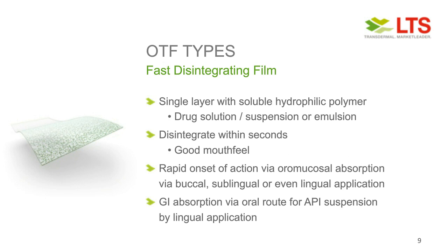The fast disintegrating films can achieve a rapid onset of action, mainly via the oral mucosal absorption of the drug. This can be achieved while the film is applied buccally, sublingually, or even by just a lingual application. It really depends on the permeability of the drug. But with the fast disintegrating film, we can also achieve just another oral application, basically, with the absorption through the GI tract, when the API is not very well water soluble, for example, and it's just suspended in the film, and this can be achieved by a lingual application as well.